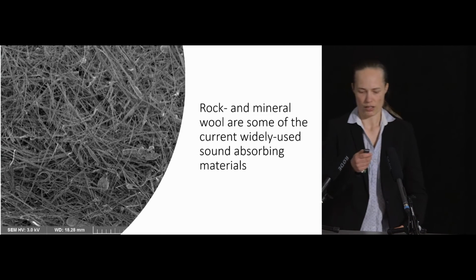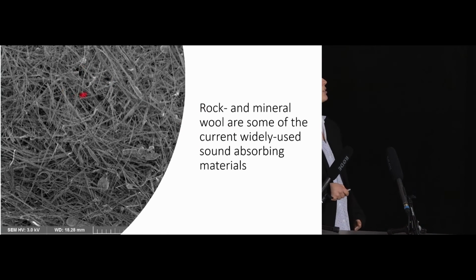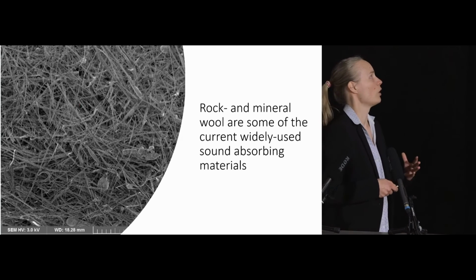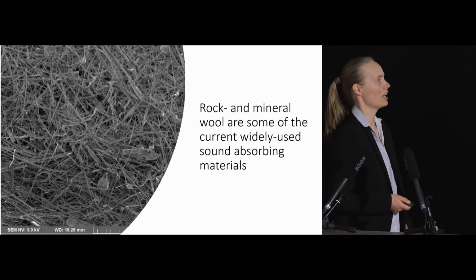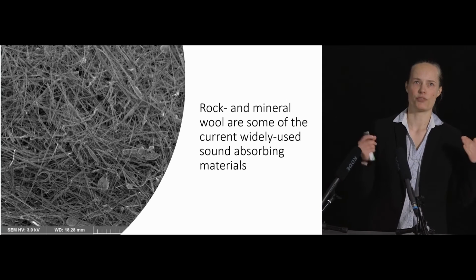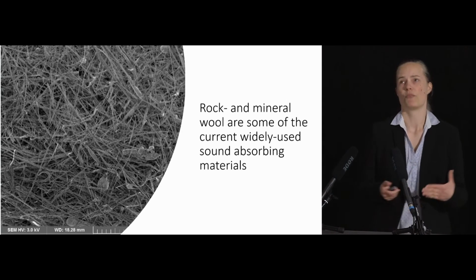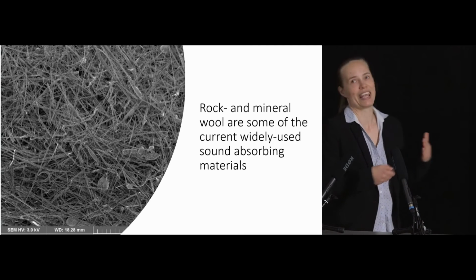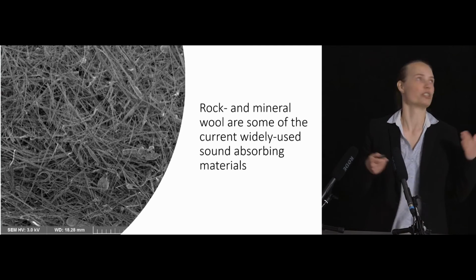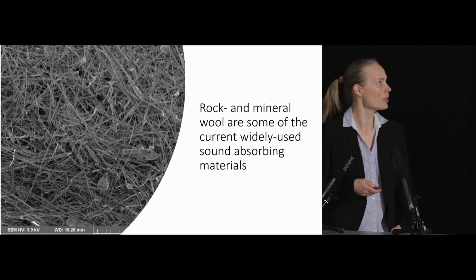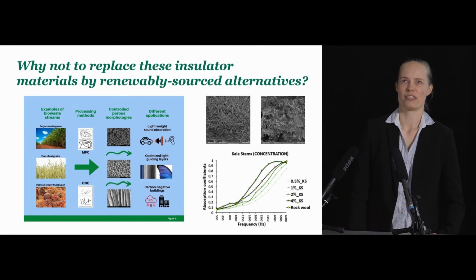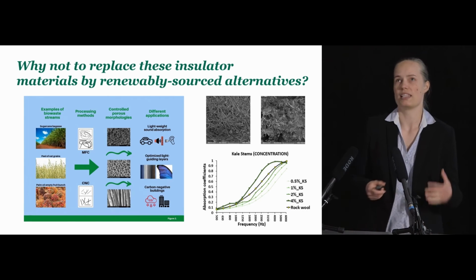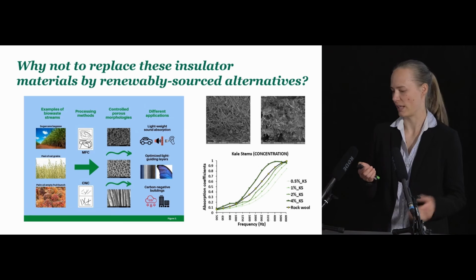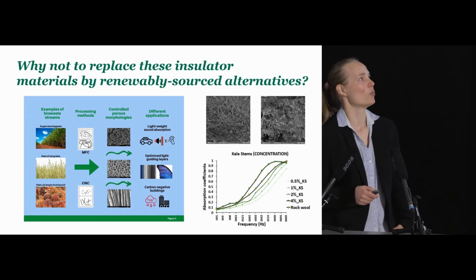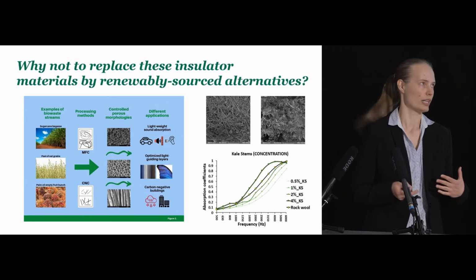But when you look at their structure, here is a scanning electron microscopy image of rock wool. You can see that it's pretty much just a network with a lot of air pores and voids inside. So this gives you a hint that this type of sound dampening property probably stems from just having a lot of air-material interfaces and interaction of the sound wave at those interfaces. This is good news for us because as materials designers, it's quite easy for us to design different types of porous networks.